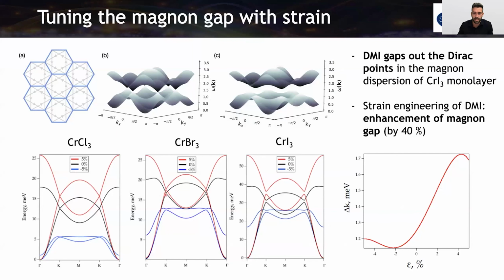In the case of chromium bromide 3, it's a little bit in the calculation, but especially here is clear. And with a strain, we can directly control this opening of the gap. So we are here reporting the evolution of this magnon gap because we are playing directly with the Dzyaloshinskii-Moriya interaction. So it makes an enhancement of the magnon gap by 40%. This is also a new way of practicing a strain to control directly a magnon gap in a 2D magnetic material.